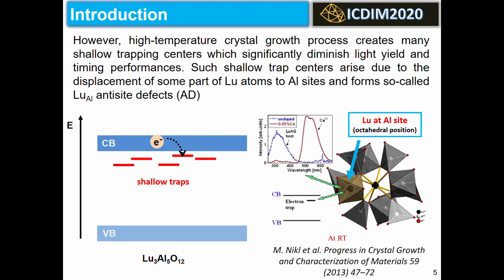However, the high temperature crystal growth process creates many shallow trapping centers which significantly diminish light yield and timing performance. Such shallow trap centers arise due to the displacement of some part of lutetium atoms to aluminum sites and form so-called lutetium-aluminum antisite defects. Lutetium at aluminum site increases covalency in the octahedrons. At critical values of non-Coulomb potential, the energy levels of cation or oxygen split off into the forbidden gap, forming electron